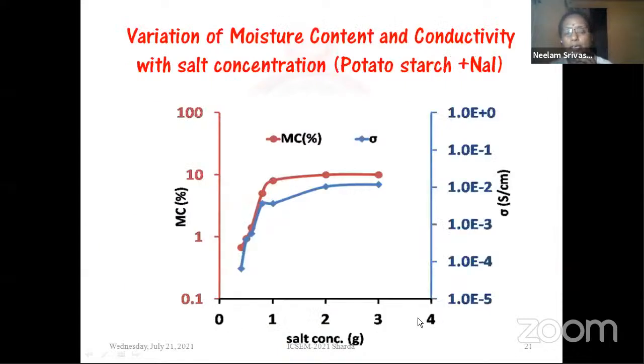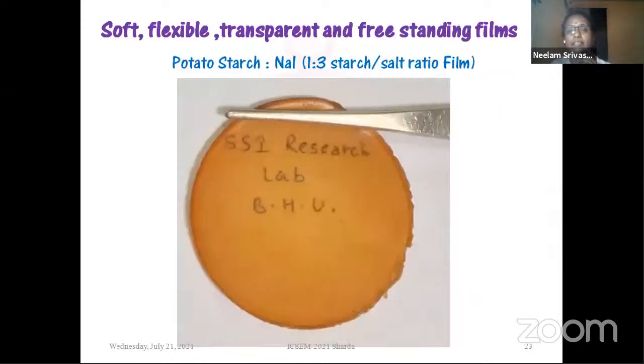This is the total salt concentration variation. You can see that after 0.6, 0.7 gram of salt, the conductivity has reached a very high value. This is the conductivity, and this is the moisture content. And of course, the moisture content has also increased, but please remember this moisture is in a bound condition, so it doesn't come out in an easy form. So that is a very good thing with the system.